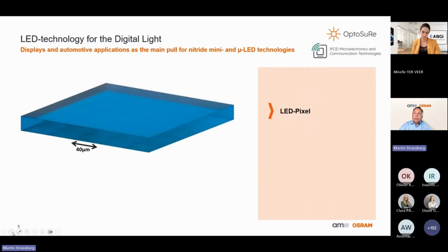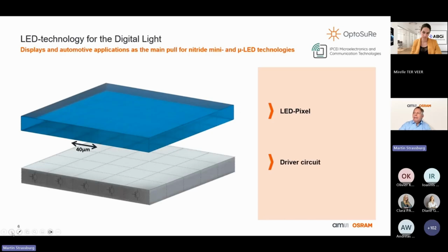Nevertheless, let me now go a little more into the detail of how we fabricate such a pixelated micro LED. What you can see here in blue is an epi layer. It is made of gallium nitride with an indium gallium nitride emitting zone. And you can imagine here that the growth direction has been from top to the bottom, and the growth substrate is already removed. And we have a slight pixelation, as you can see here, of the surface of the pixelated LED. Now we want to get them in close proximity to a driver circuit and connect each pixel of the LED with a pixel of the driver circuit to have an individually addressable LED pixel.